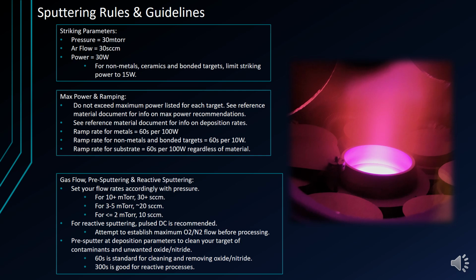For reactive sputtering with nitrogen or oxygen to form oxides and nitrides, I recommend you use pulse DC for any compound that's a dielectric. When performing reactive sputtering, it's wise to try and establish a maximum flow rate of reactive gas before the target poisons. For more information on this, see the link in the description for the Intro to Sputtering presentation. This is somewhat advanced and will be taught more in person upon request.